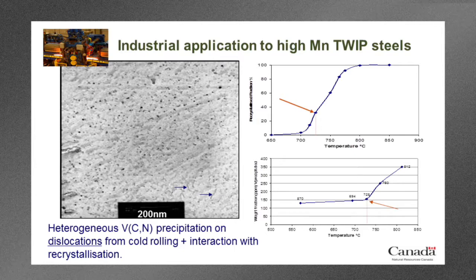If we look in more detail, again, this is another extraction replica. What we did was interrupted heating after cold rolling, with heating and quenching experiments. So we're looking at how the vanadium precipitates between the end of cold rolling and the start of the isothermal holding during the recrystallization annealing, and how it affects the recrystallization kinetics. First thing I would point out in this extraction replica image is that some of the very fine precipitates seem to be aligned. You can see them here. I've marked them out with two little arrows.